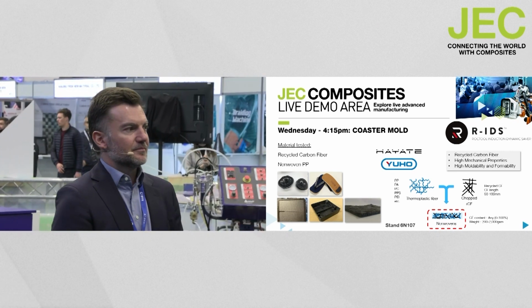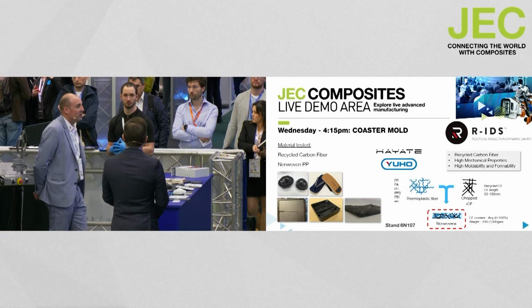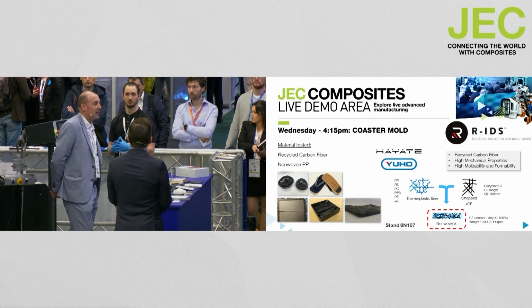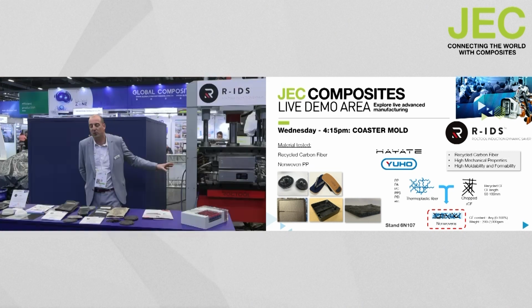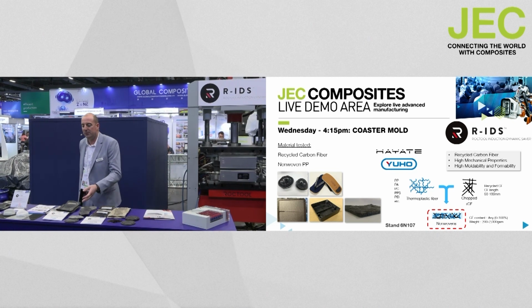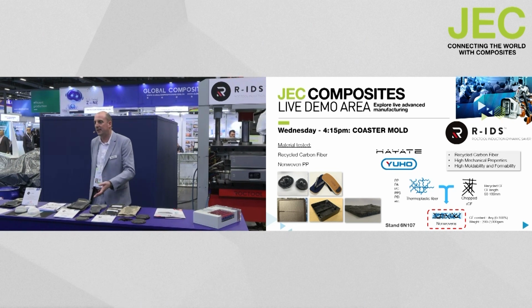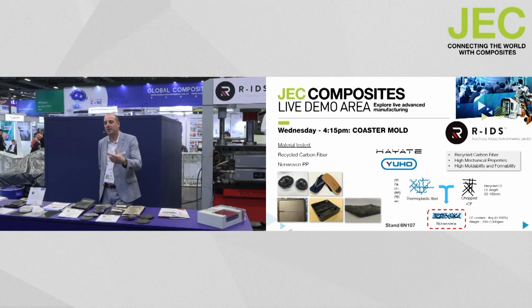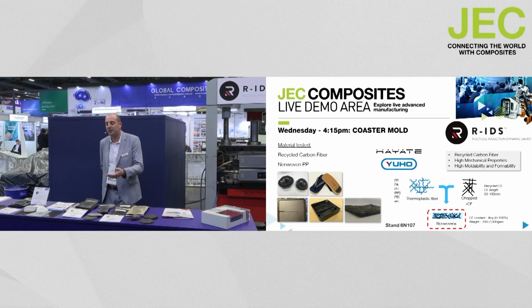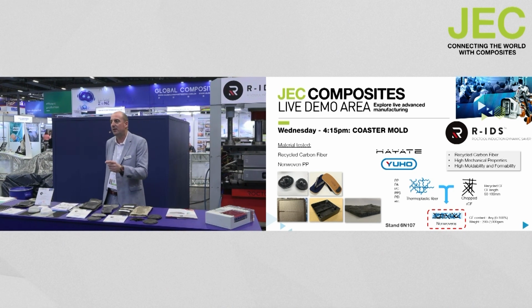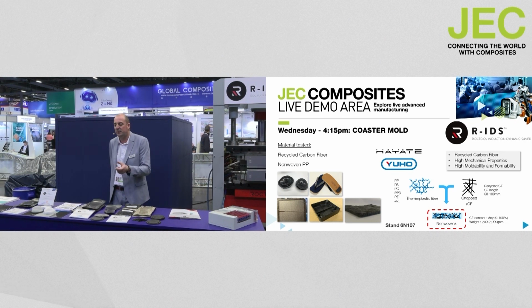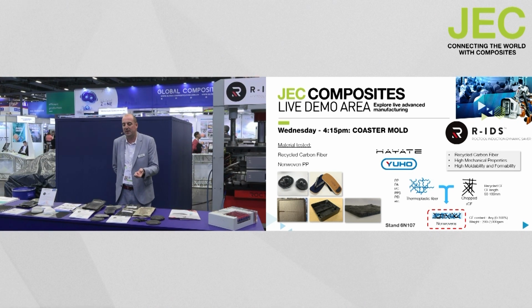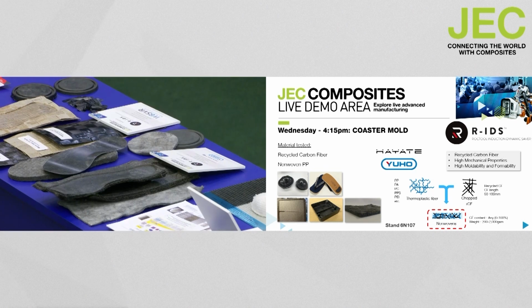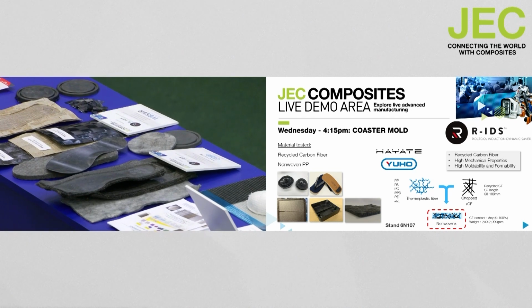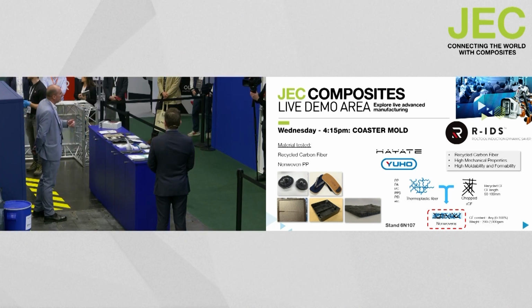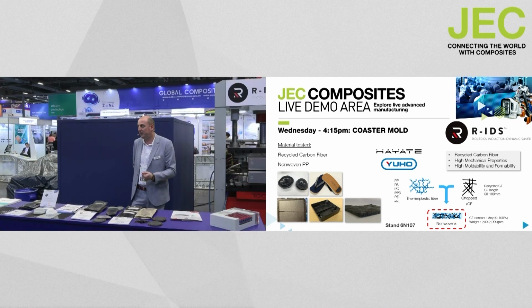Clearly, we can adapt the RIDS technology to a very large range of different materials. So for this live demo, we present the use of Hayate material, which is a non-woven recycled carbon fiber, with the particularity of having a carbon length between 50 to 100 millimeters. It's a good material also for drapability and formability, with very good mechanical performance.